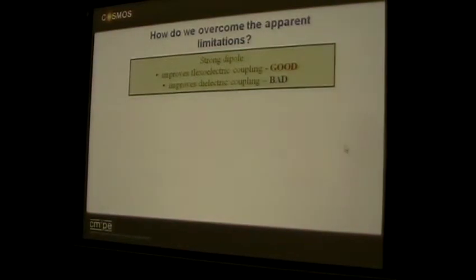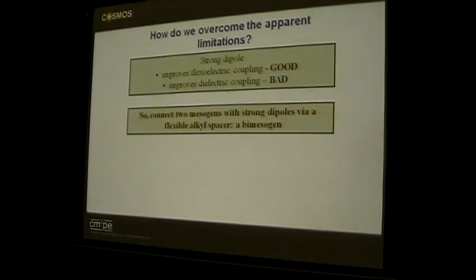You need a strong dipole, because that gives you polarization. That would give you good flexoelectric coupling, but it also increases the dielectric properties. So you want a system that has a big dipole, but a low delta epsilon. So how do you do that? We make what we call bimesogens, liquid crystals with 2 liquid crystal groups.